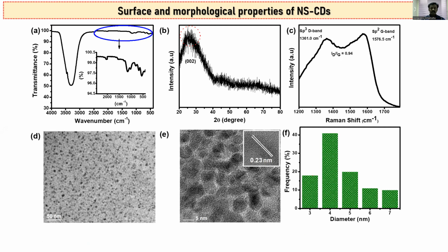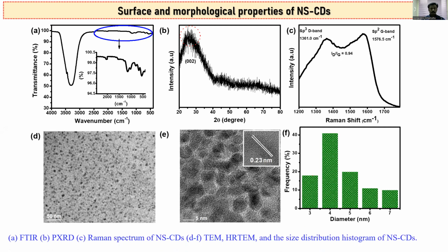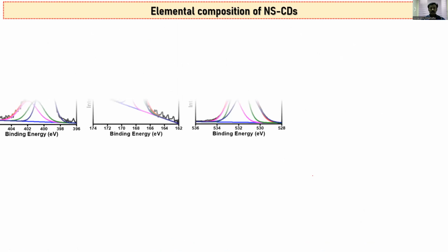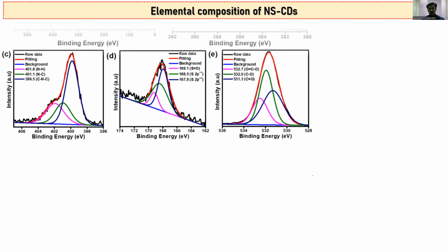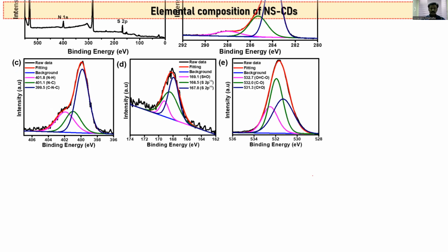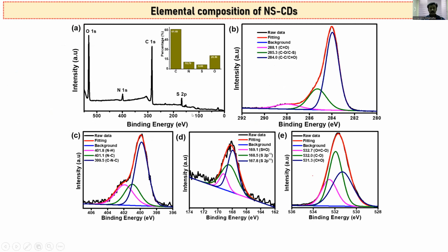Okay, the next one is the XPS analysis, elemental composition. So this is the survey spectrum. The survey spectrum of the carbon dots shows 4 different peaks: nitrogen, carbon, oxygen and sulfur. We also get the elemental composition percentages. The highest is carbon at 61.69%, and nitrogen is 10%. Sulfur is 6.6%, and oxygen is also 20%.